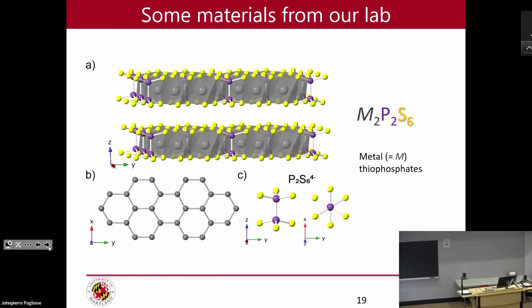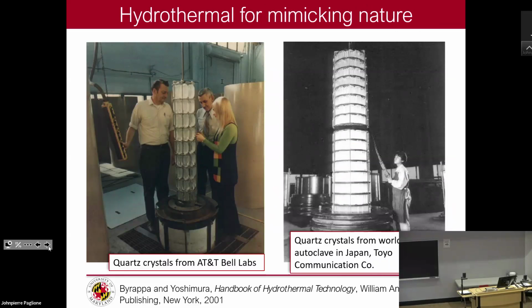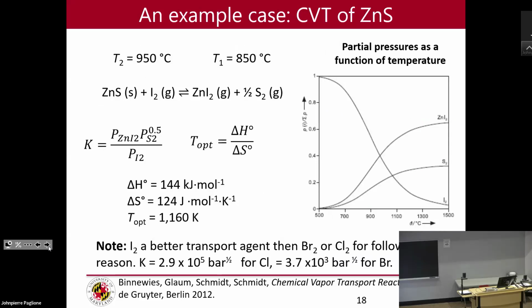Let me see, what I wanted to say is, let me go back, whoops, going too fast, is transport agent. So this is an example of zinc sulfide. You want to think about some kind of transport agent that's going to be part of your reaction, right? Many times we like to choose halides or halogens in the elemental form, like iodine, chlorine, or bromine. I would say, always try to figure out what would be the easiest thing to manipulate in the lab. So with iodine, it's a solid at room temperature. You can pick up a little crystal, weigh it, and then put it into your glass tube or quartz tube and seal it, right? It's not a big problem.